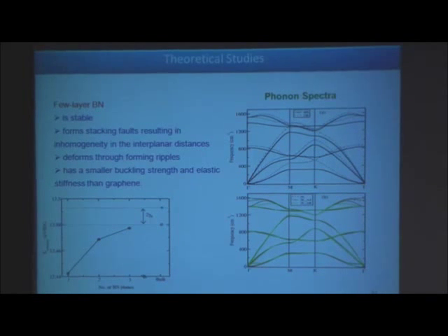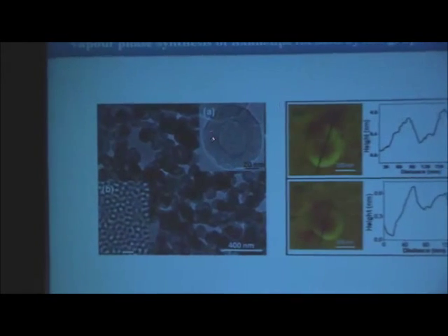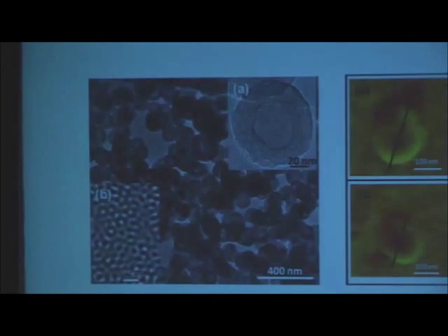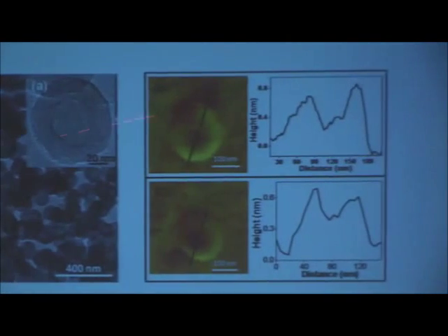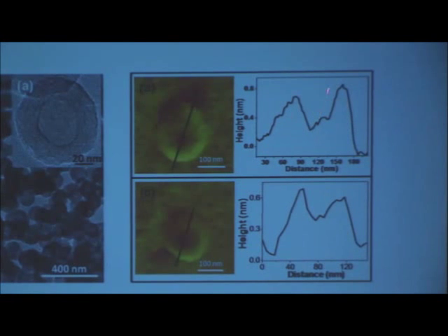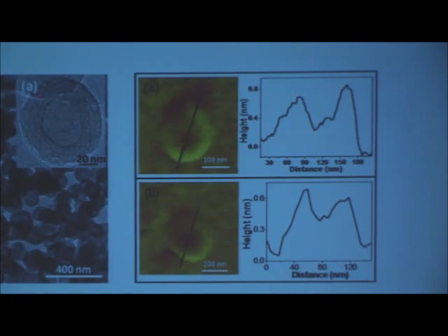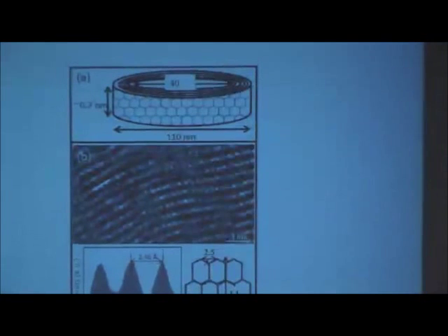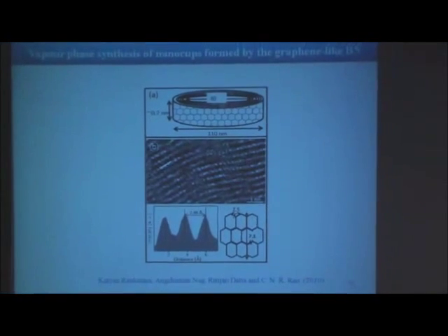Of course, as usual, I told you, always I do theory. We have done all the electronic band structure of boron nitride as a function of number of layers. Will not bother you. But we have recently made boron nitride nanopans. Nice nanopans, the diameter is only 40 nanometers. You can see the pan, the edges go up, and in the center it comes down. It is a very nice pan that can be made. I'll not worry about the description of the pan.